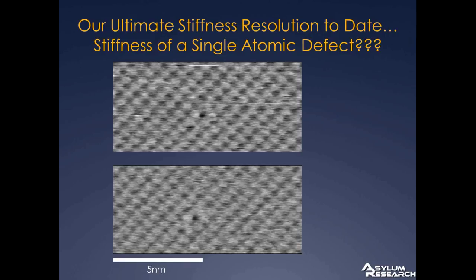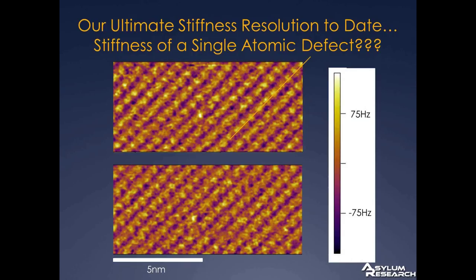There are about 5 or maybe as many as 10 images in between. You can see that maybe the contrast has changed a little bit as the tip modifies and changes, but to give you an idea that this was a stable defect that we were able to resolve. At the same time, we were imaging it in topographic mode with the first mode of the cantilever. We were measuring the stiffness with the second mode. And that map is shown right here.